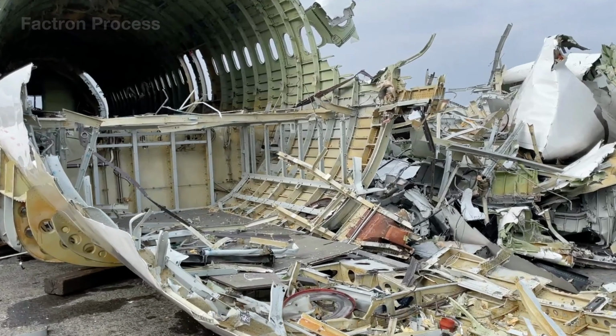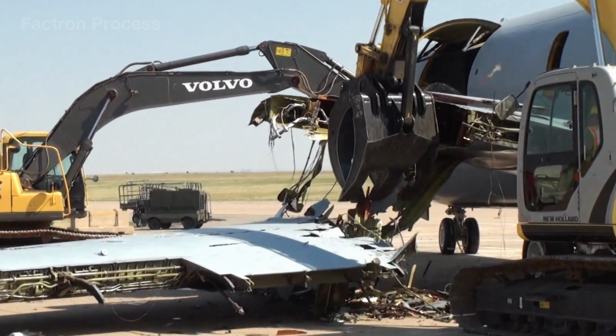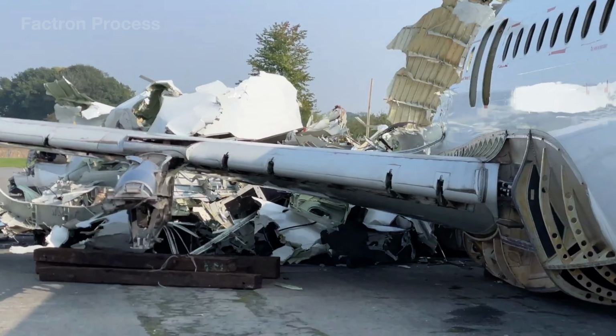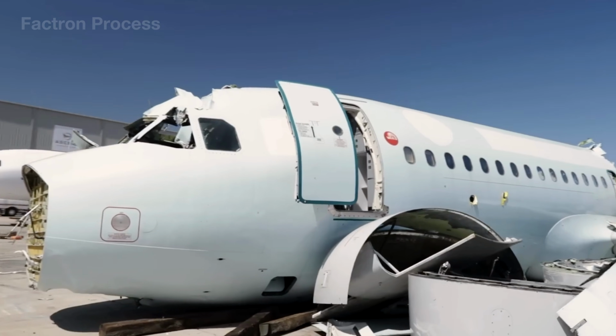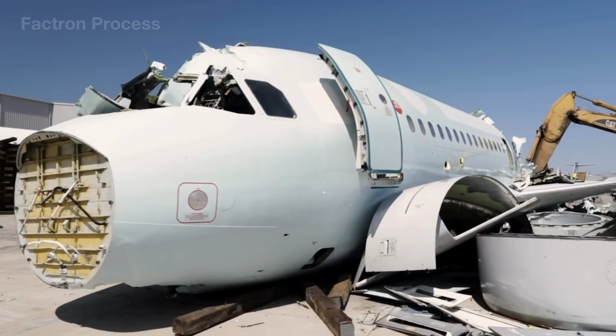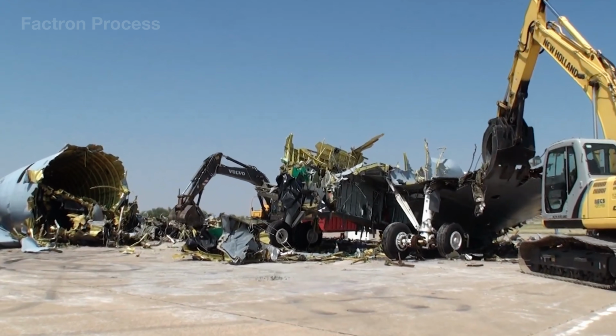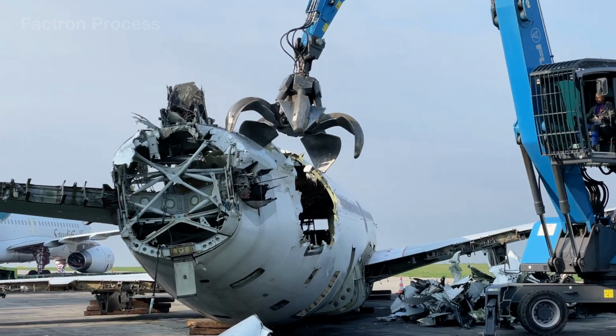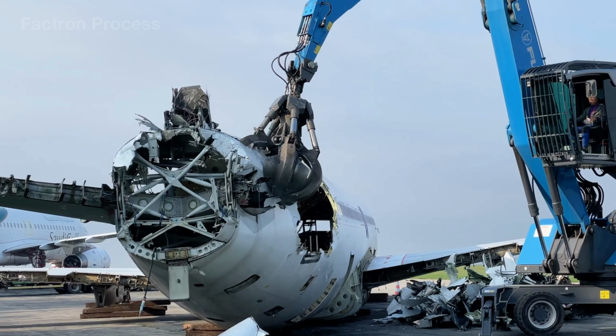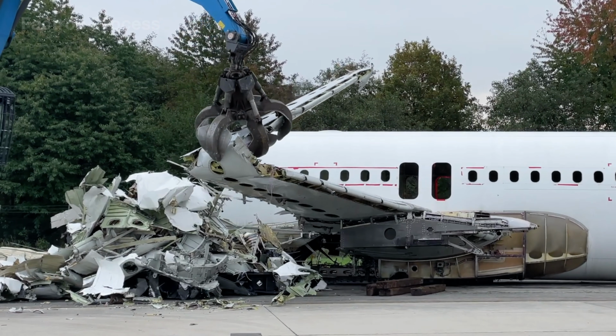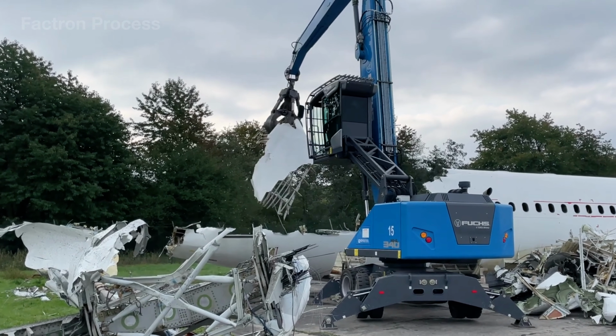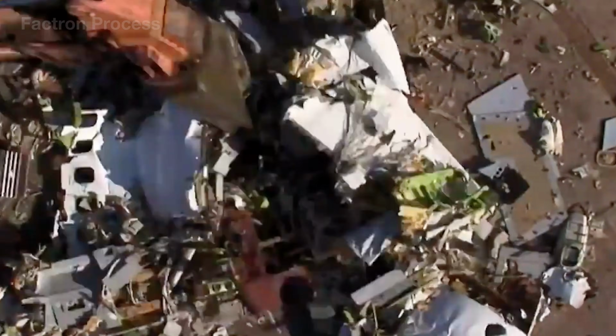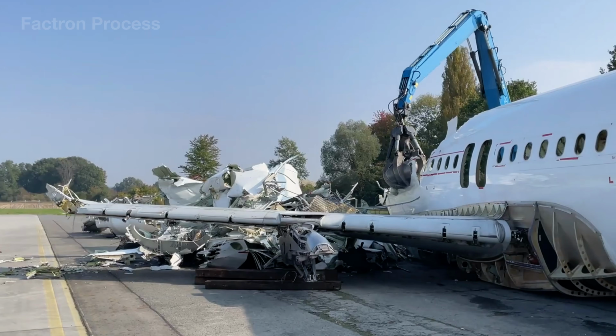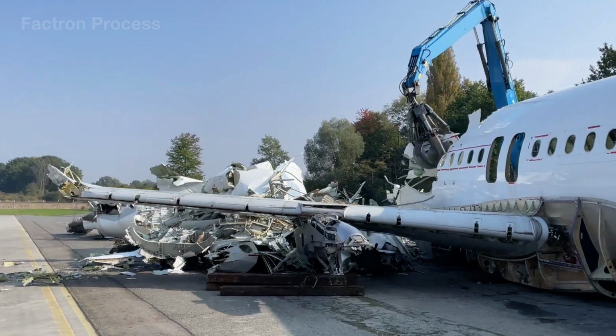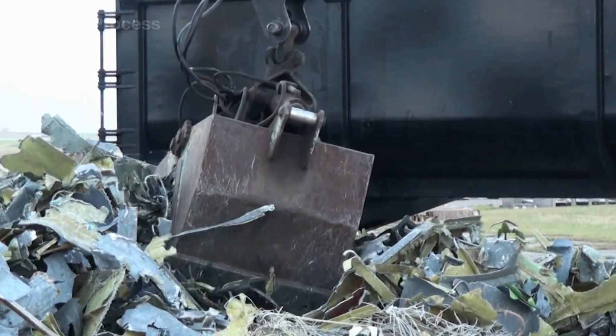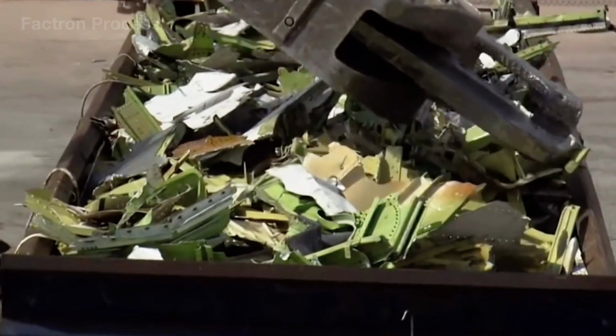In an Airbus A320, approximately 72% of the airframe consists of aluminum and aluminum-lithium alloys, alongside around 9% steel and 6% titanium. The more completely these materials are separated at this stage, the greater their recovery value becomes. Within a short period, a fuselage nearly 40 meters long can be transformed into thousands of pieces of scrap. Yet this is not simply a chaotic pile of waste. At modern facilities, around 90 to 92% of an aircraft's total weight can be recovered or recycled.